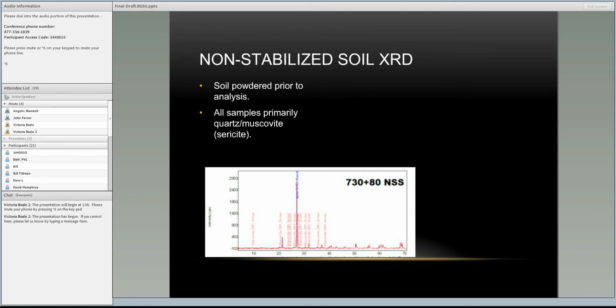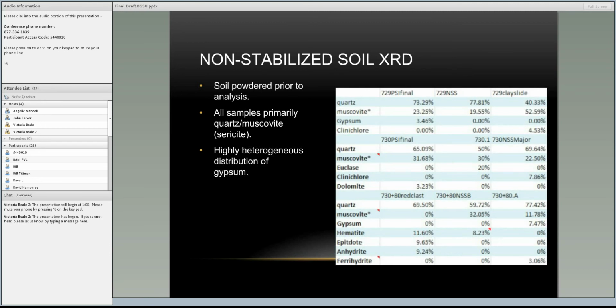And what we found is there is gypsum in the non-stabilized soil, but kind of like what we found with sulfate testing, the gypsum is very heterogeneous. It doesn't show up in every sample that's run. So up at the top here are 3 729 samples, 3 730, and 3 730 plus 80. You can see primarily in all of these, quartz and muscovite are what's primarily making up the non-stabilized soil. There is some gypsum here that was found in 729, and then I believe, yes, some anhydrite down here in 730 plus 80, and then we have a lot of clays like clinochlore. Some of that was found in 729, 730. So again, non-stabilized soil, primarily quartz and muscovite.